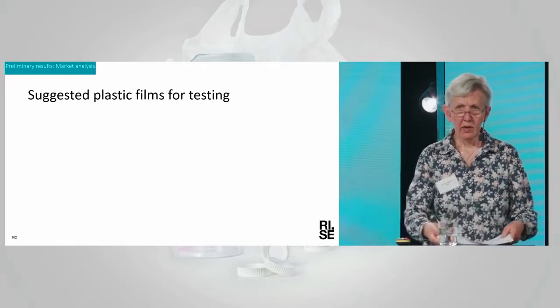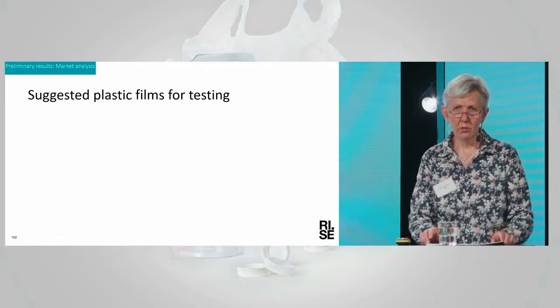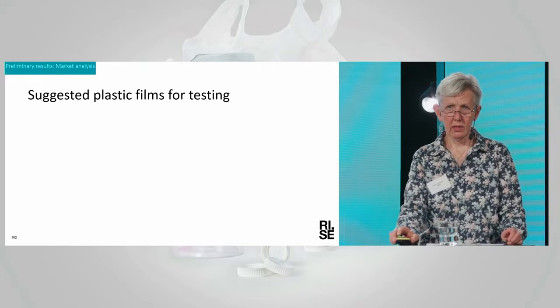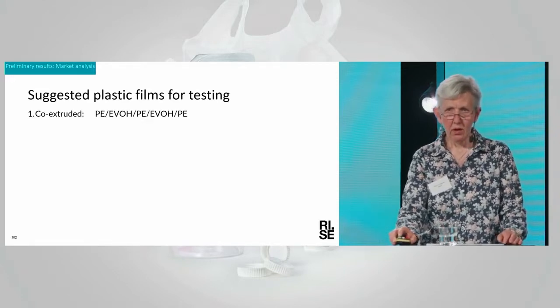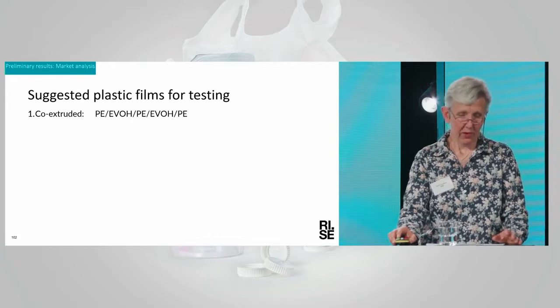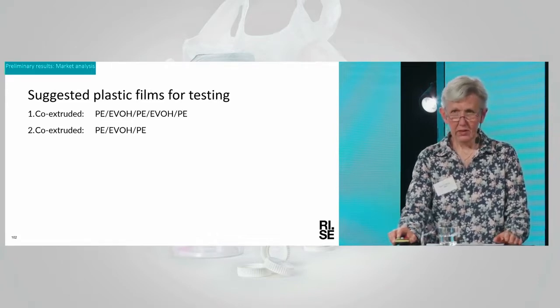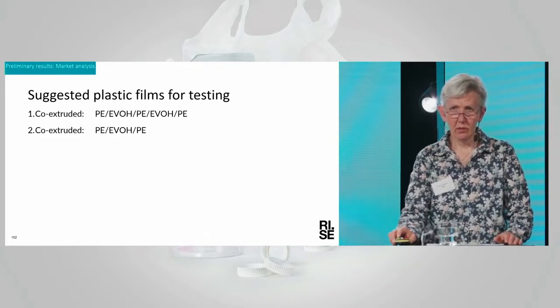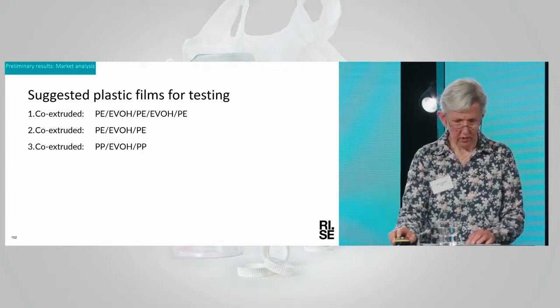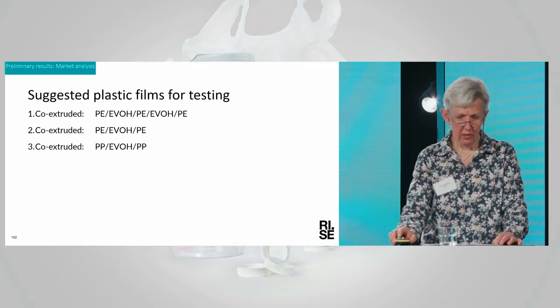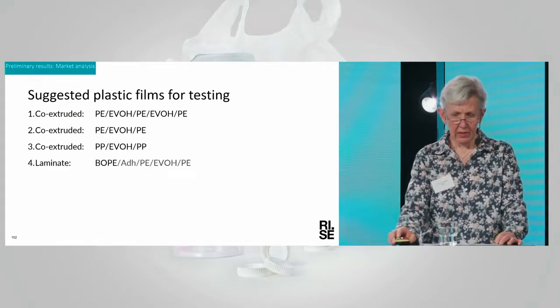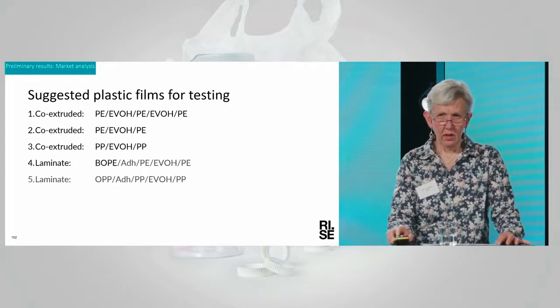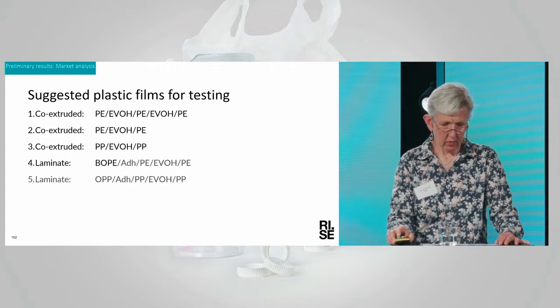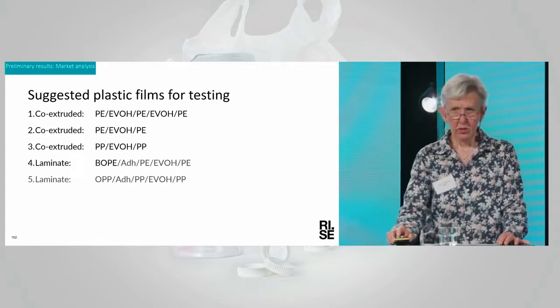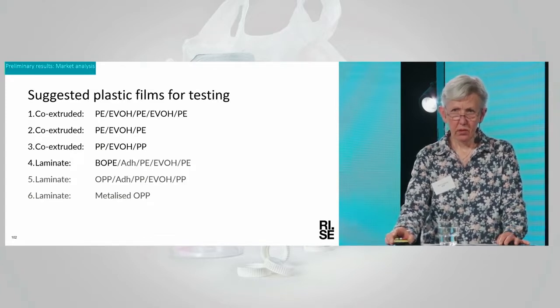So we have collected suggestions of films to be tested for both sorting and recyclability. So we have here co-extruded polyethylene and EVOH with different number of layers. This is actually the same material in the second suggestion, but different number of layers. The corresponding or the same, but PP instead of PE. We look at laminates with adhesives. Yes, so with oriented film. And also we will have a look at metallized oriented PP.